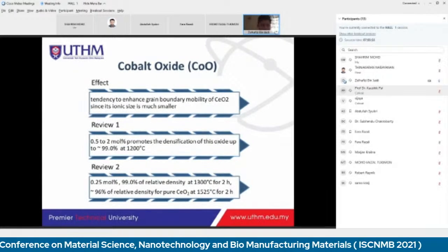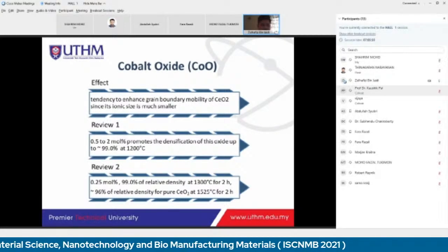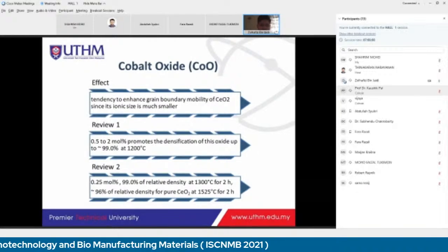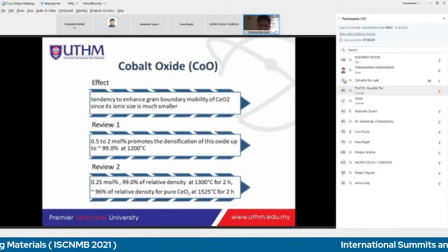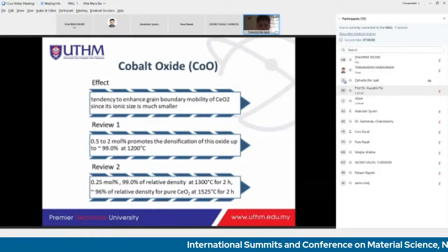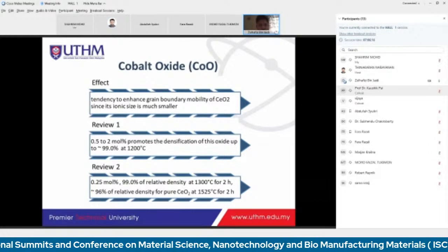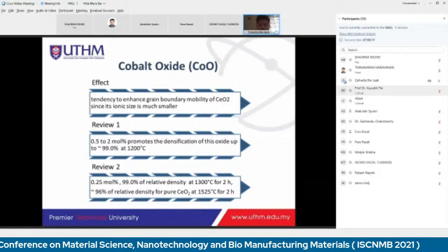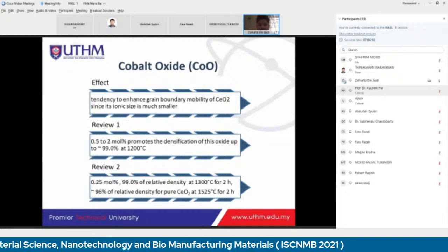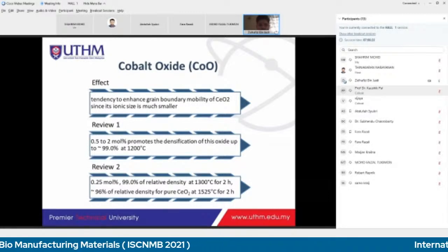For cobalt oxide, the effect is that cobalt ions have the tendency to enhance grain boundary mobility of the ceria oxide, since their ionic size is much smaller than that of the ceria. From one of the reviews that I read, 0.5 to 2 mole percent of cobalt oxide can promote the densification of samarium-doped ceria to 99%